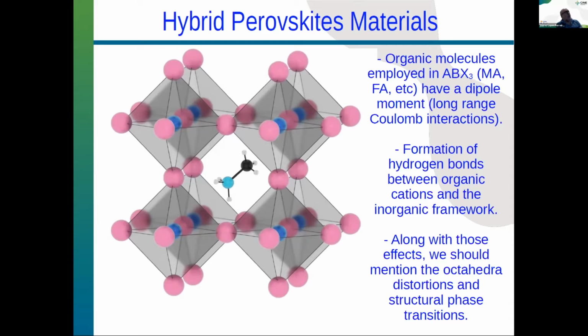Second point, the formation of hydrogen bonds between those cations and the inorganic framework. And this makes the organic molecule more displaced in the direction of the octahedron, for particular cases depending on the termination of the molecule. And along with all those effects come the structure phases. With all those effects together, they will compete to stabilize those structures. It is really quite a challenge here.